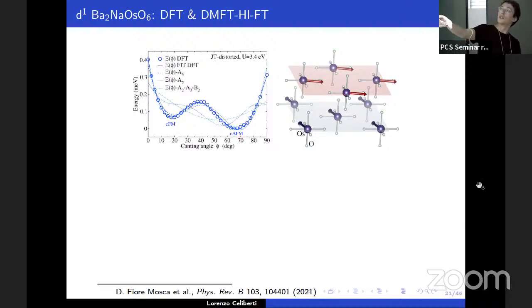So you can see, these blue balls are the osmium atoms with magnetic moments aligned in the XY plane, and you basically vary the angle on the plane, rotating these magnetic moments like this. And what you observe is this curve showing a minimum at around 67 degrees for the canting angle. This is in agreement with NMR measurements, which gave 66 degrees for the canting angle.